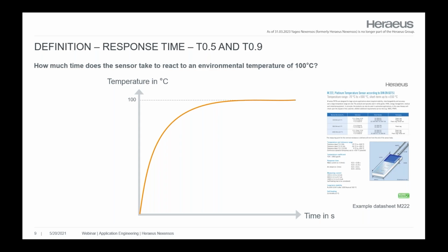So let's take a look at the graph. You can see on the x-axis the time in seconds that the sensor takes to react, and on the y-axis the temperature in degrees Celsius. Let's take the example of an M222, which is a really standard sensor element from us. When we take a look at the term T05, it would take, in this specific example, the sensor 0.05 seconds to detect 50% of the final temperature. 50% is in that case 50 degrees Celsius. And the same for the T09: that would take our M222 0.15 seconds to detect 90%, and therefore 90 degrees Celsius, of the final temperature.